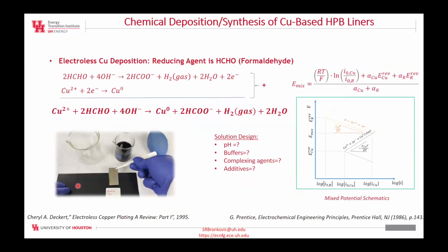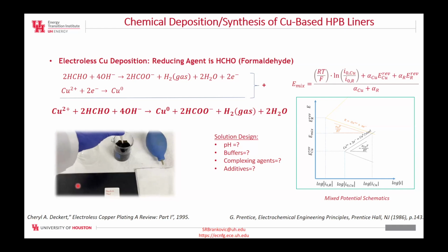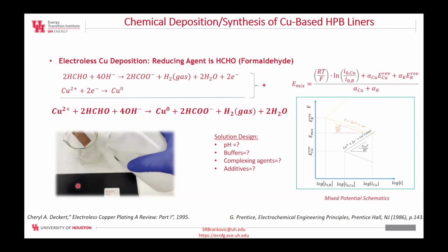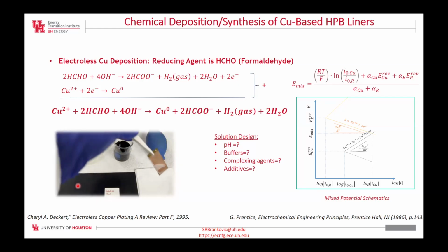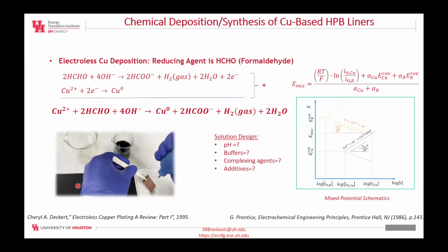So here I give you an example why we go with the chemical deposition of copper permeation barriers. It's basically a very simple process where you have chemical reduction of copper ions in the solution with reducing agents. Could be formaldehyde, could be something else. The bottom line is that you can achieve pretty fast and pretty high quality copper coatings on steel, which are relatively cheap as compared to any alternatives. And this could be scaled up fairly easy to any kind of a geometry, size. And it is, in general, a process that's been around for about 100 years, well understood. And what we really need to do is just fine tune the process to achieve the quality and, I would say, density of the copper coating that is appropriate for this application.